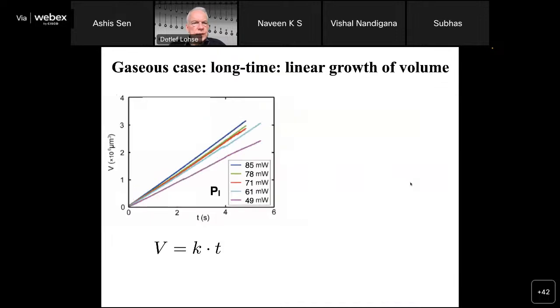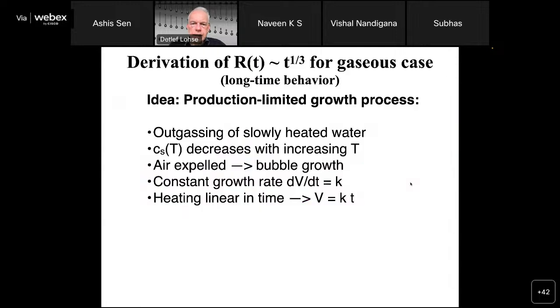So how to explain this? Well, simply the volume is linear in time, and it's simply outgassing. So this is, so to say, a production-limited growth process. You outgas the water by simply heating it. By heating, you decrease the solubility of gas in water, and therefore the water has not much of a choice but to expel the gas. And where does the gas go? Well, it goes, of course, to this nucleus, which has been formed by boiling, to this vapor bubble. So in the beginning, you have a vapor bubble, but then the liquid around the bubble warms up, can take up less gas, and therefore you will have growth of this bubble. And then the constant growth rate implies that the volume simply increases linearly in time.